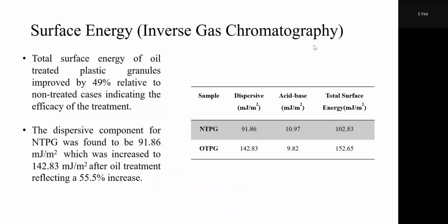So this is right here another tool. We use inverse gas chromatography, and with that, we measure basically surface energy. The non-treated one here had, in terms of dispersive forces, 91 millijoule per square meter. As soon as we treated it, it became 142. So you can see the change in dispersive forces, and of course it reflects in the total, which is increased. The increase of surface energy promotes interaction with surrounding material. In this case, we're going to put plastic into bitumen. So the increase of surface energy of our new plastic helps it interact with its surrounding, which is bitumen. That's the hypothesis, right? If I increase the surface energy, if I grafted this molecule, I'm expecting that the interaction will go up.